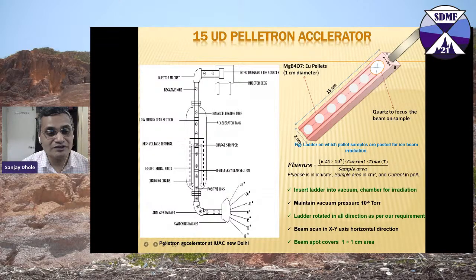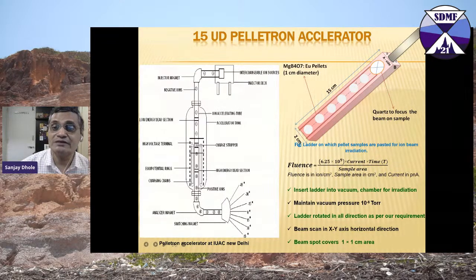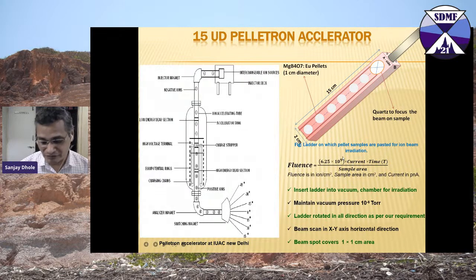And this ion beam goes into the magnetic analyzer, which measures the energy, and goes into the different beam lines. One of the beam lines is dedicated to material science, where this kind of work can be carried out. This is a sample holder. You can keep your nanophosphors for ion irradiation, more than 20 samples together, in four ways, and you can rotate it. This kind of holder can be operated in vacuum. The vacuum can be maintained around 10⁻⁶ torr, and everything is controlled from the control console.